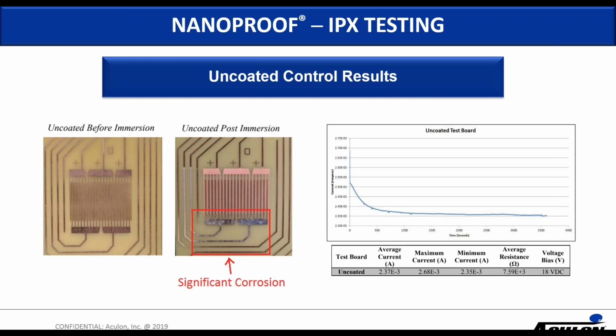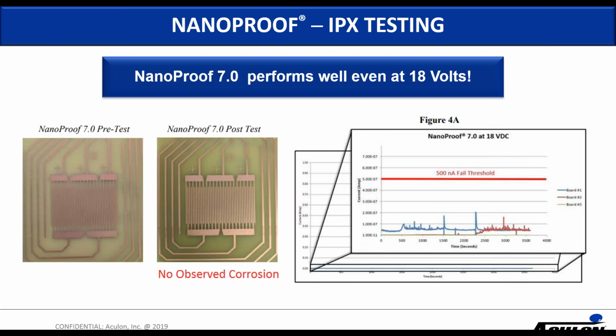Here's an example of a control coupon. Before immersion, it looks great, and then after immersion, you can see there's extensive corrosion. It's essentially a failed part, and the current leakage is incredible from the get-go, and the current leakage actually falls off because the part is failing, and so less current is flowing because the part has become so corroded, which is as we would expect.